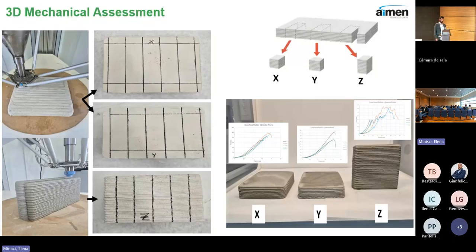And finally, it's also important to check mechanical properties because we are talking about building materials, so durability and mechanical properties are important. And in the case of 3D printing, it's also important to analyze the anisotropy, because 3D printing generates some anisotropy depending on the printing direction. So this is something that we study in our projects. We printed 3 different slabs in the 3 different directions, X, Y, and Z. And we cut each slab into specimens, and we carried out compressive and flexural tests. And we observed that in terms of compressive strength, there is no significant difference, but in terms of flexural strength, we saw that the Z direction is the lowest, followed by the Y, and the X is very, very close to a specimen manufactured with a traditional casting method.